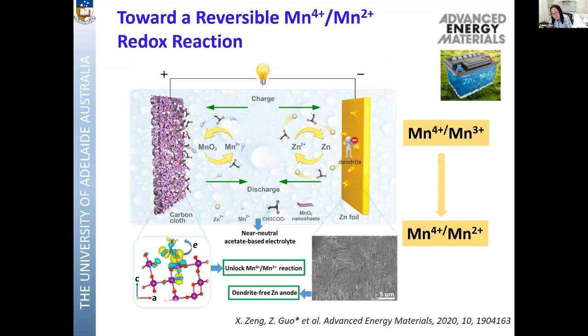And we found that this electrolyte not only influences the zinc deposition behavior, but also influences the cathode material reaction. You can see in the traditional zinc sulfate electrolyte, manganese oxide has a 1 electron transfer reaction from manganese 4+ to manganese 3+. So it's a solid reaction. Therefore, it suffers from manganese dissolution and also phase transition. However, by using acetate, we can unlock the manganese 4+ to 2+ reaction, making it a deposition dissolution reaction. So it means from solid to liquid to solid.